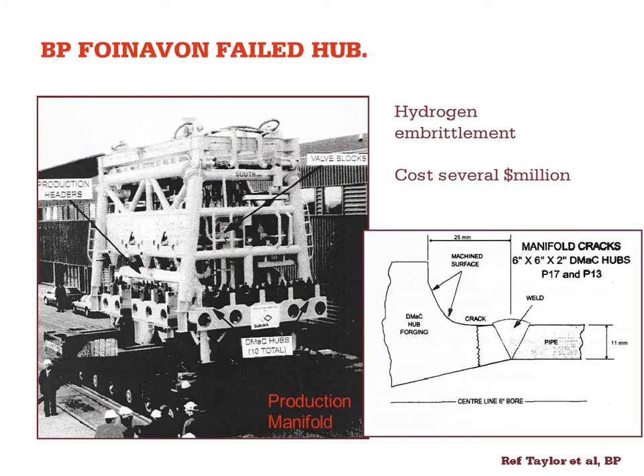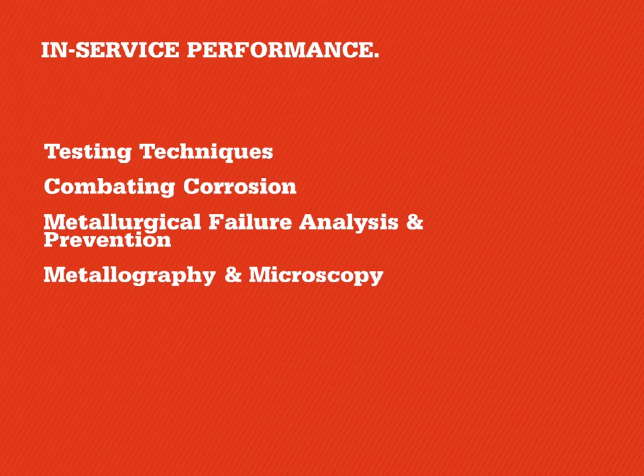And in fact, that was the cause of the British Petroleum Foinaven failure, which was a very famous failure. It cost a very large sum of money, and that was due to hydrogen embrittlement in a weld, which wasn't picked up, it wasn't detected. The product, the manifold, went into service and subsequently failed. So a lot of this, the processes and the materials that we deal with have to be carefully controlled and understood for very good industrial reasons.